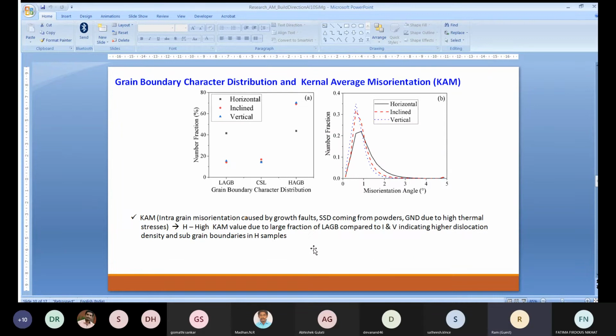Then we also tried to understand the grain boundary character distribution and, as I said, the kernel average misorientation. So you can see the low angle grain boundary, the high angle grain boundary, and the coincidence site lattice. Though the coincidence site lattice fraction is very low and its importance is not felt here, it is surprising to see CSL character grains in an aluminum kind of alloy, which has a high stacking fault energy.